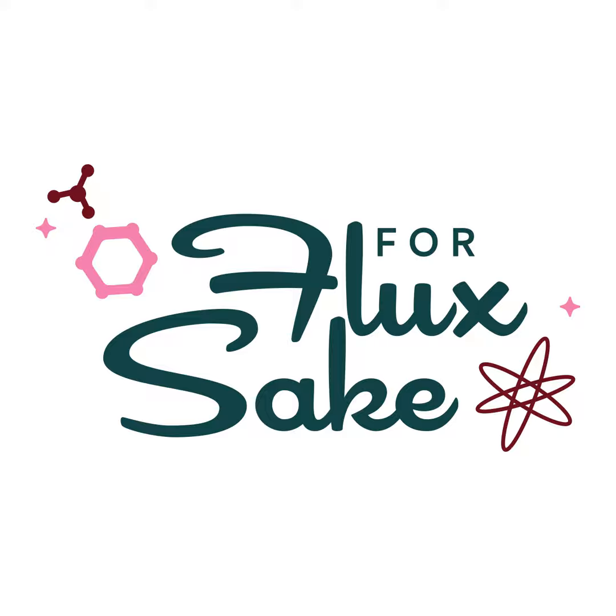Okay. Ryan Coppage did a study that he published in Ceramics Monthly back in 2018, where they tried to embed bacteria into crazes, and then they put it through modern sanitation, and it all cleared away. So it really isn't a thing. The bigger problem is crazing makes work substantially physically weaker. And one of Dr. Cardi's graduate students, Brian Pinto, had done a study on it. And work can be up to 75% weaker in the fired state if it's crazed, because those crazes cause what we call a critical failure location, where if there's stress, if you're doing a cheers and you tap your mugs together, that force will ripple through the crazes and will cause the pots to break.